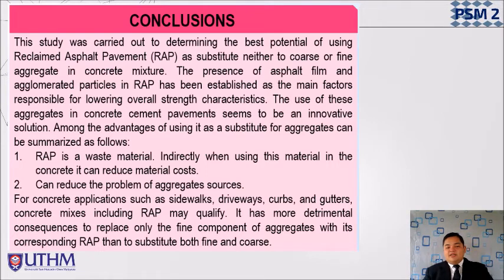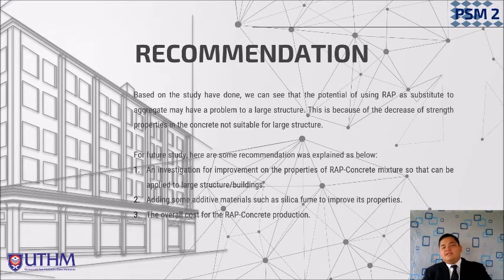For concrete applications such as sidewalk, driveway, curb and gutter, concrete mix including RAP may qualify. It has more detrimental consequences to replace only the fine component of aggregate with its corresponding RAP than to substitute both fine and coarse. I can conclude that the usage of RAP in concrete mixture is good for non-load bearing structures. The recommendation for upcoming studies, based on the study done, is that the potential of using RAP as substitute aggregate may have problems for a large structure. This is because of the decrease of strength properties in the concrete, not suitable for large structures.